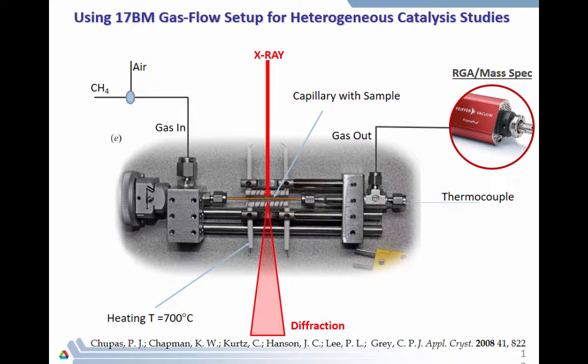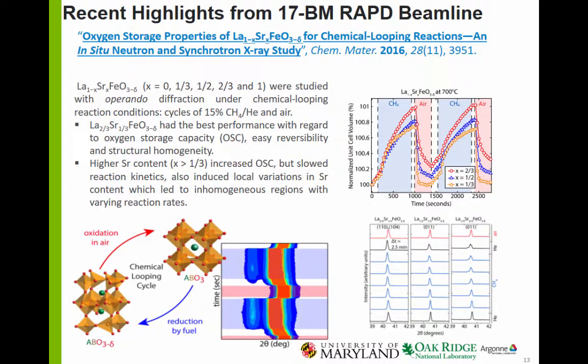Such a study has also been done quite recently at our beamline, where they studied lanthanum strontium iron oxide for its oxygen storage properties, and they were able to very clearly see from powder diffraction how the material structure changes upon oxidation or reduction. At the same time, they combined the data with a residual gas analyzer, and they ran several samples and were able to determine at which doping of strontium into this oxide will give them the best results.